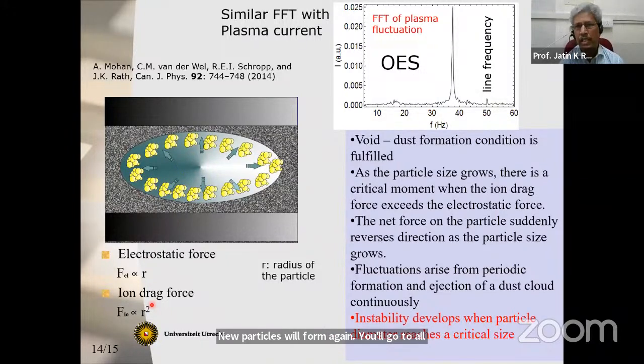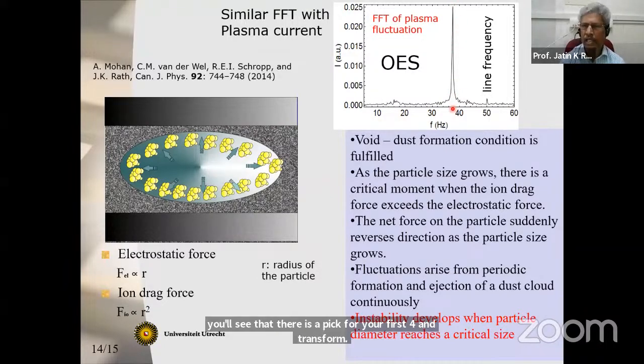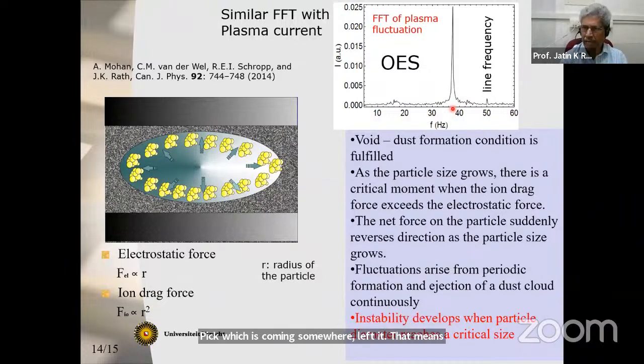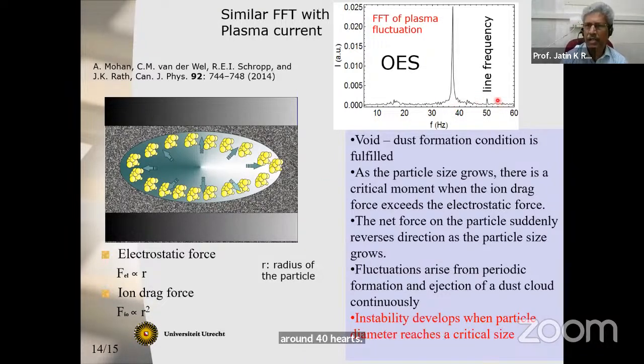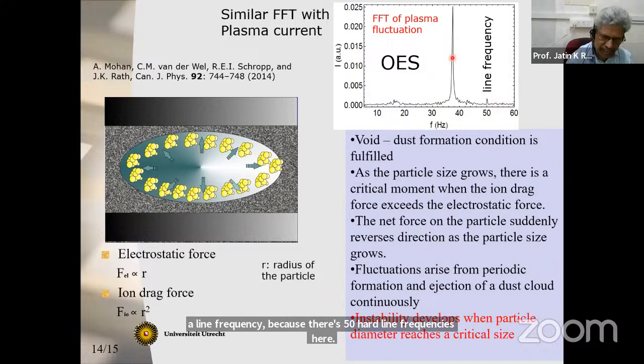You can see this frequency through optical emission spectroscopy. The plasma light also goes with some frequency. Also, the plasma current goes with a frequency. If you take the fast Fourier transform of the plasma fluctuation, either from OES or from the plasma current, you'll see a peak in the fast Fourier transform, let's say around 40 hertz. These particles are formed, detrapped, again formed, and detrapped. And also there's a line frequency, because there's a 50 hertz line frequency here. So this is the frequency at which the particles are formed inside and detrapped.